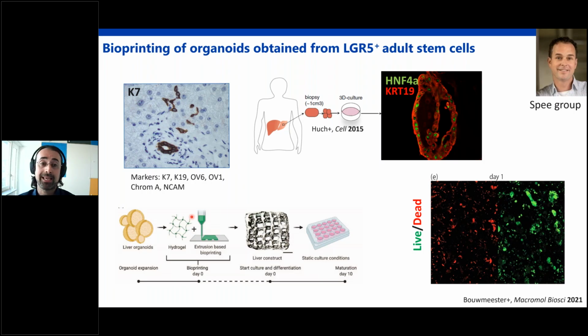However, we quickly realized that if our printing blocks are not single cells, but relatively large aggregates, which are also quite fragile, as you can appreciate, they are hollow inside, so you have a thin monolayer of cells and then a hollow cyst inside. These are quite fragile, and the shearing through the nozzle is actually sufficient to shed cells of the organoids and cause significant death. Now, of course, these cells will recover after a few days of culture, so you can still use these models to test drugs on them, for example, but you can appreciate that this is not really ideal.